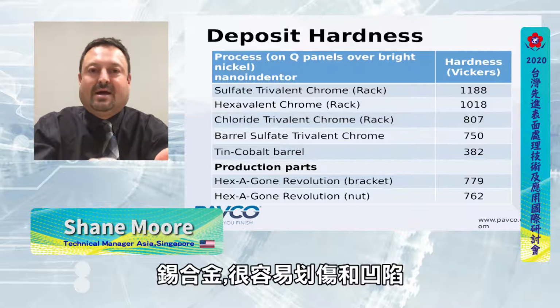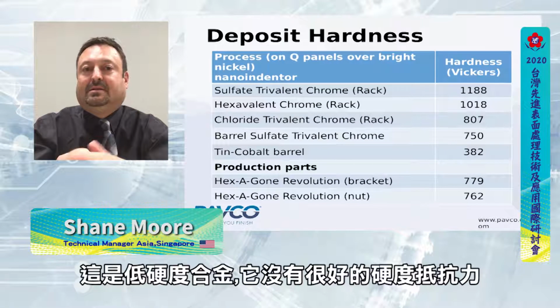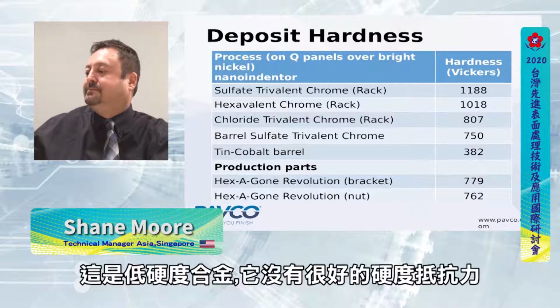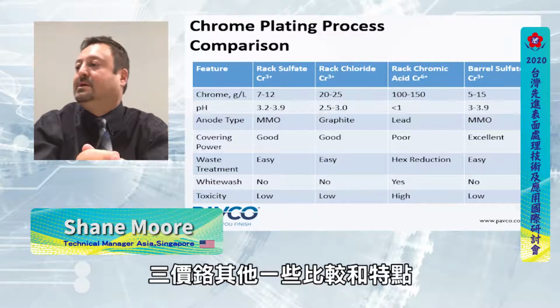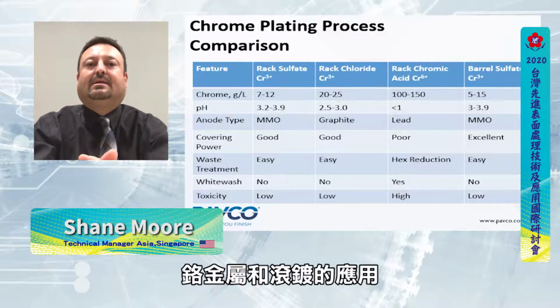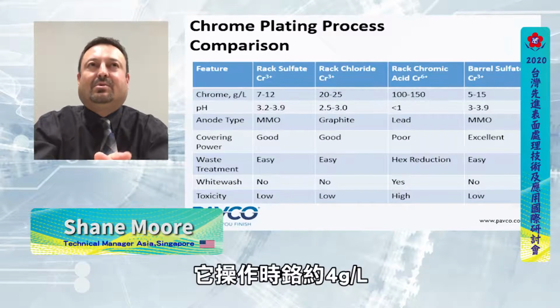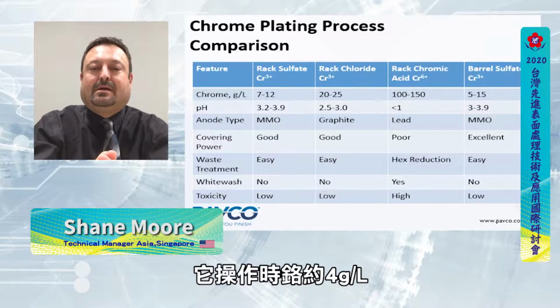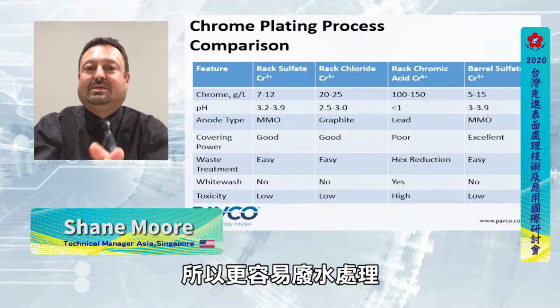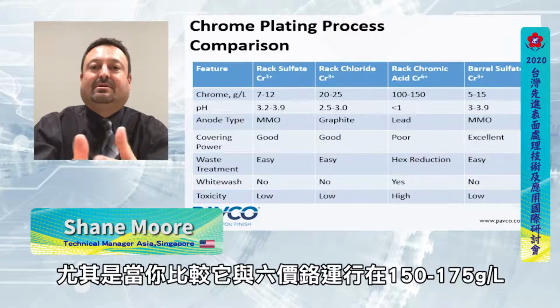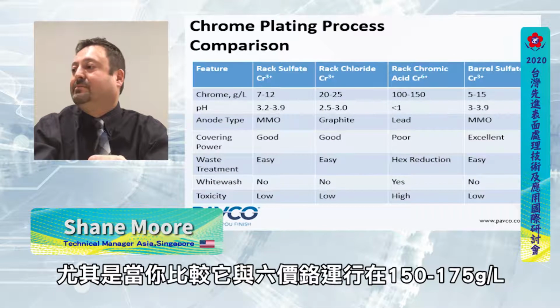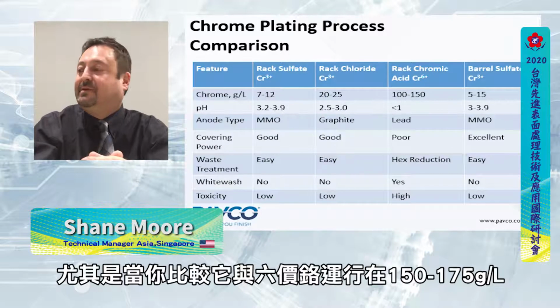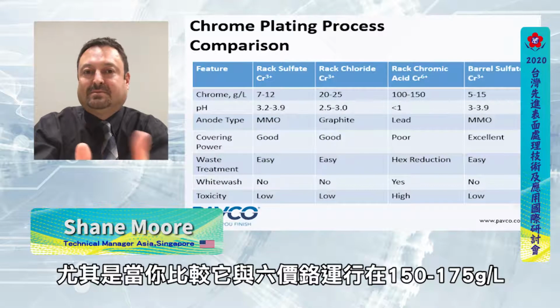And so it's easy to scratch, it's easy to dent, and it's just a much softer deposit and not quite as resistant in a few other comparison characteristics. The chrome metal in the barrel application runs around 4 grams per liter, so that makes it much easier on waste treatment, especially when you compare it to hexavalent chromium, which runs at 150, 175 grams per liter.